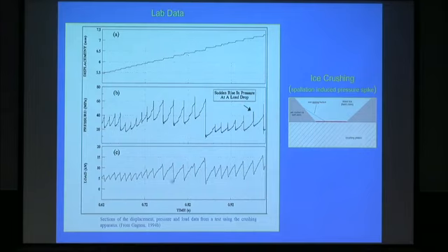On the ascending parts of the saw teeth, the indentation is slow, or the amount of ice getting out of the way is slow, and then during the sawtooth or the load drops, you get a ratcheting effect. So the relative movement of ice and platen is very fast, many times that of the nominal value.